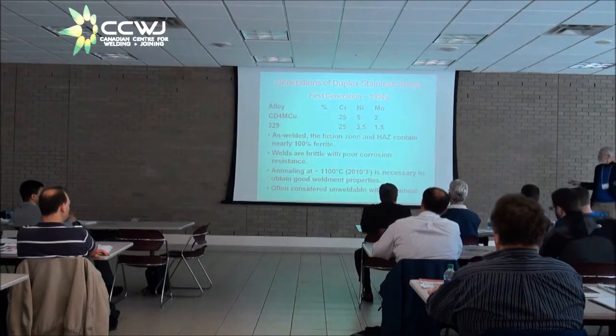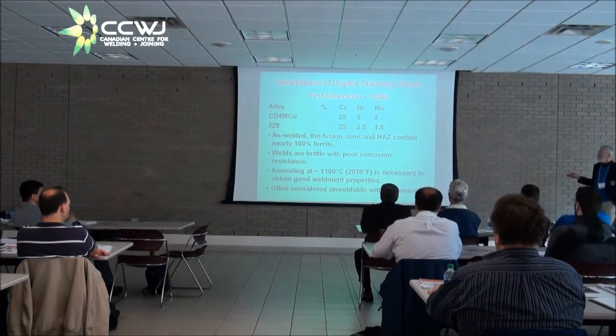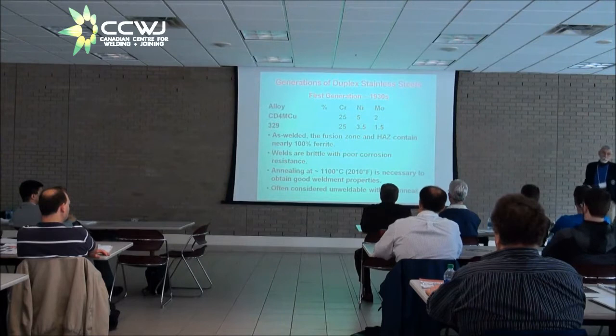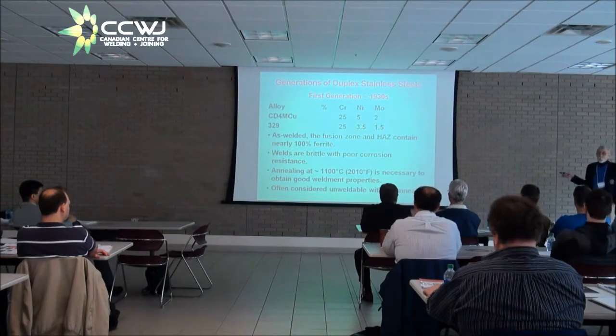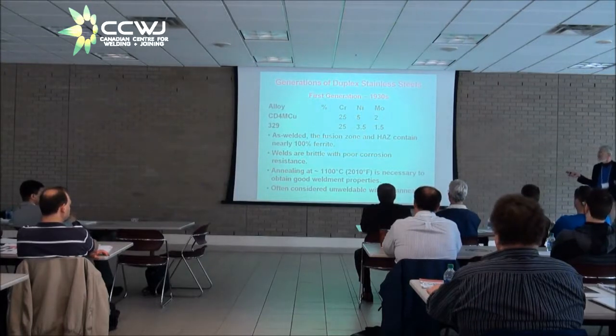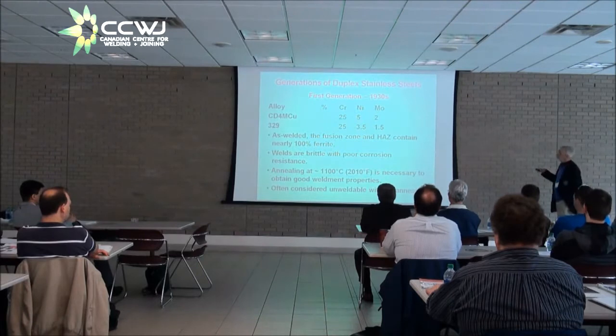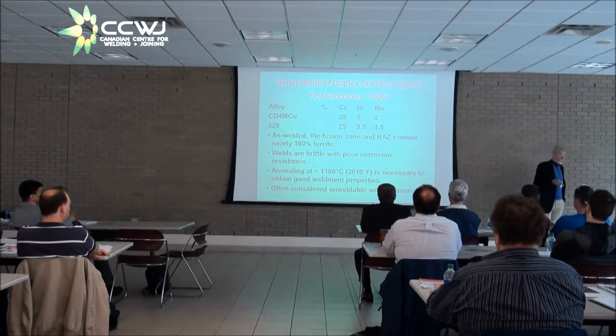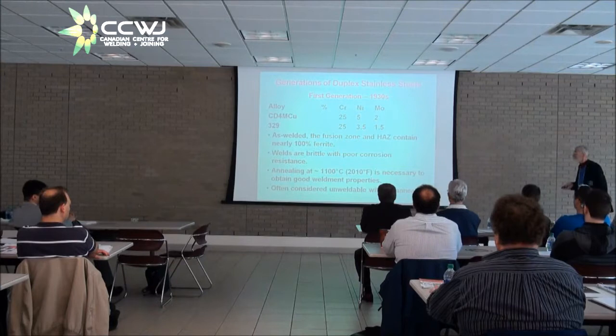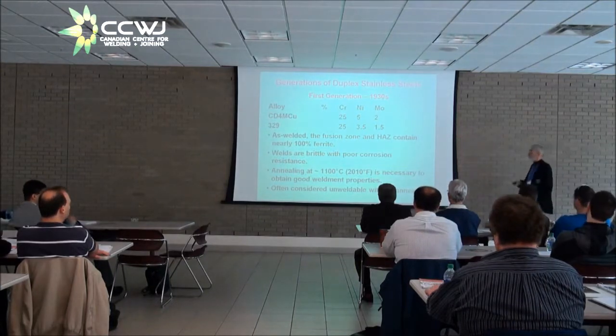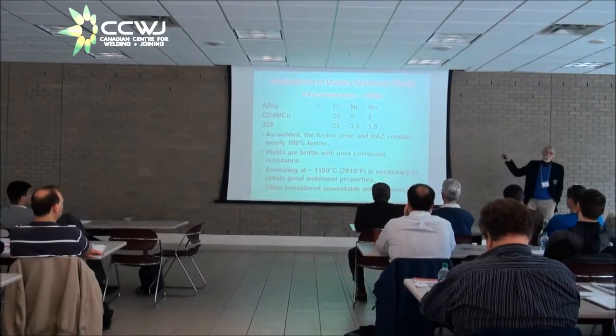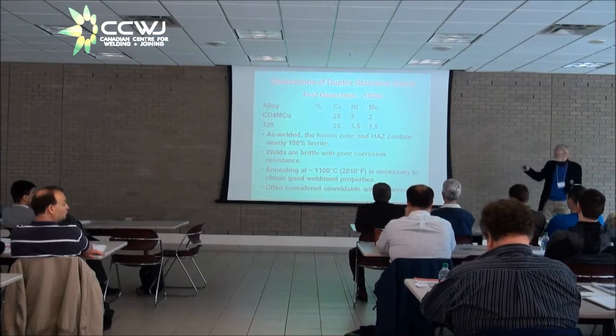The problem is that you get, in the as-welded condition, virtually 100% ferrite, and then the properties are those of a ferritic stainless steel with very coarse grains. In other words, very poor toughness. Also, because there was a little bit of residual nitrogen in it, you got chromium nitride precipitates. So the corrosion resistance was also poor. You had to anneal at a temperature around 1100 degrees C or higher in order to get good weld toughness. And then what you were really doing was adjusting the balance of austenite versus ferrite.